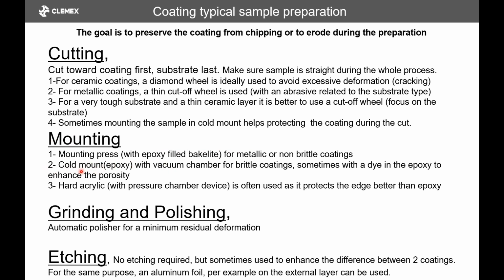And so you could use cold mount epoxy with a vacuum chamber. It's more efficient in the sense that you create a vacuum and then let the epoxy in, and it will wet into the holes, and then you let the air in, and everything will be filled up, for the porosity, of course. Sometimes a dye is used also to enhance the porosity. So if you put a green dye or a blue dye or something like that, when you polish it, the porosity will have the dye in there, so it'll be easier to find them.